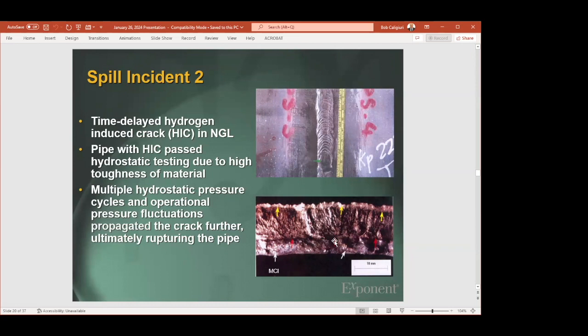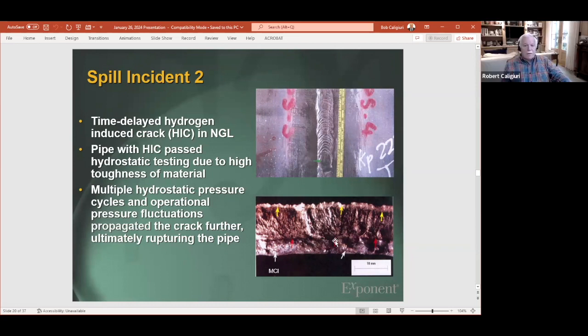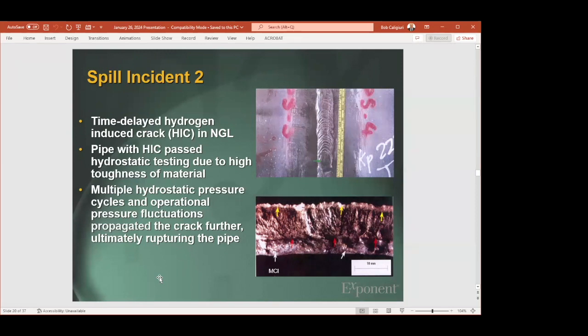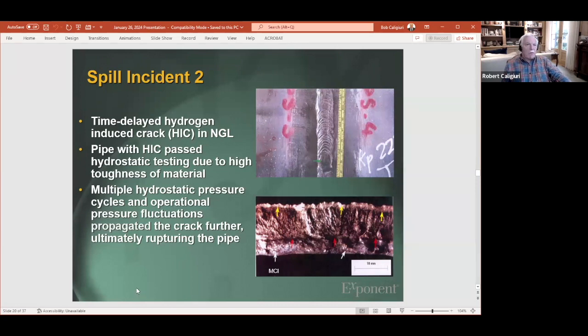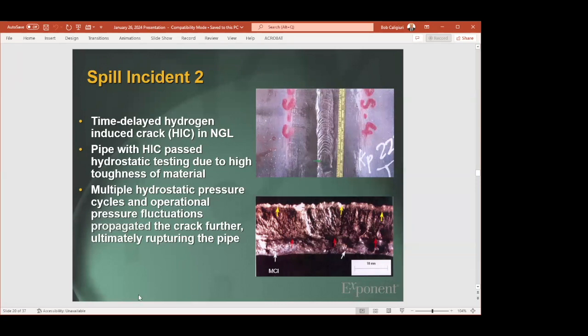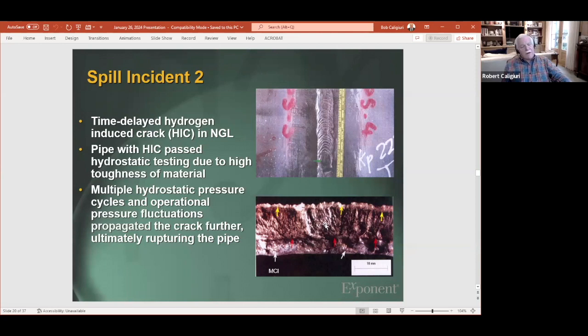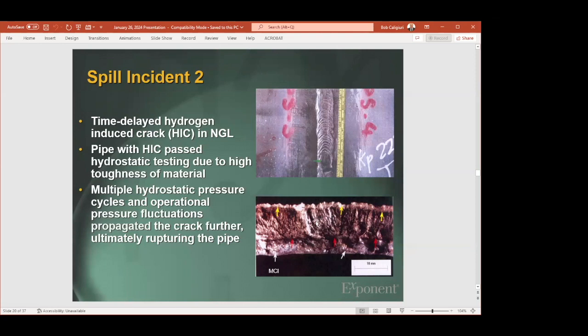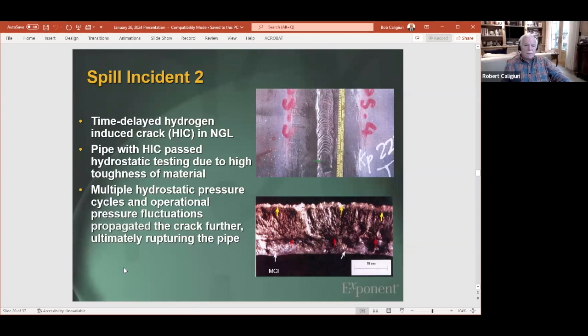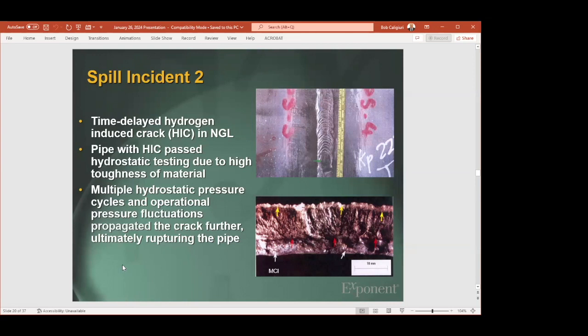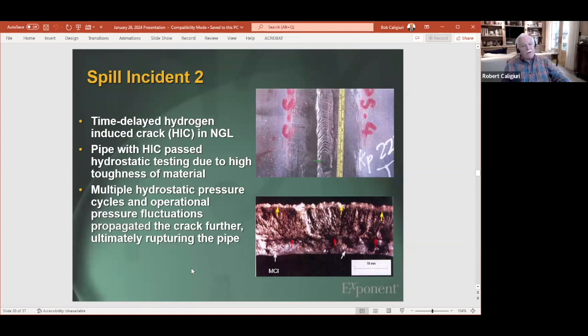It's interesting here because certainly with people operating pipeline systems, a lot of people think that hydrostatic testing is the be-all, end-all to determine the integrity of a pipeline system. Well, it can help find things that are about to leak, but here's an example of where repeated hydrostatic pressure is not a good thing, because it basically drove a dormant defect in a pipe, caused it to go through wall and lead to a failure.